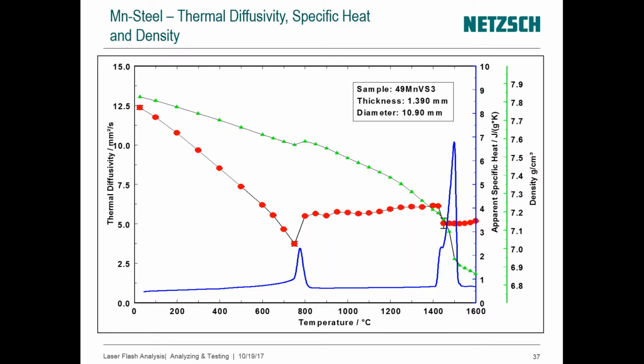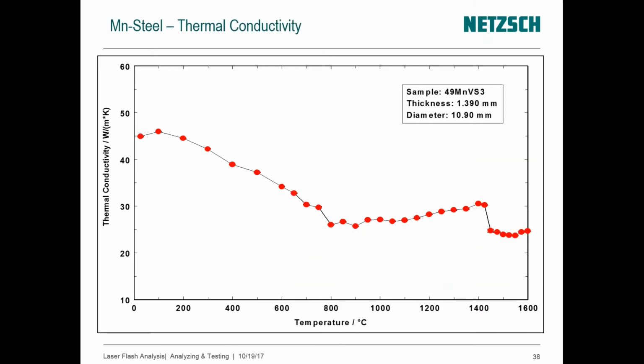So being able to monitor that through those events is really something that you probably would not be able to do so easily with a steady state method. Again, a statement for why people tend to use the LFA technique. And by the time diffusivity and specific heat and everything else is combined, you get the resulting conductivity.